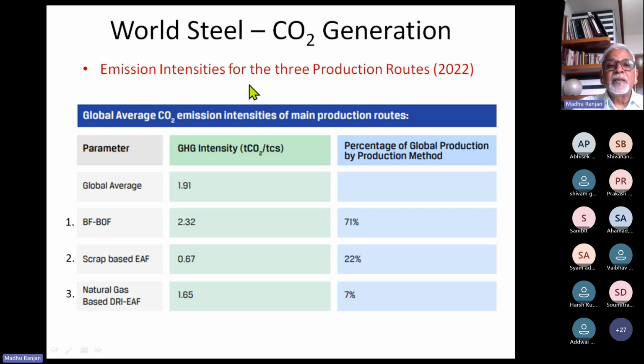Now let's have a quick look at CO2 generation at the world level. This data is from the World Steel Association. The blast furnace BOF route contributes 2.32 tons of CO2 per ton of crude steel. That is the intensity of CO2 generation. And this route has the maximum contribution to steel making, 71%. The scrap-based electric arc furnace contributes 22% of steel making in the entire world. Fortunately, their CO2 emission rate is the lowest at 0.67.